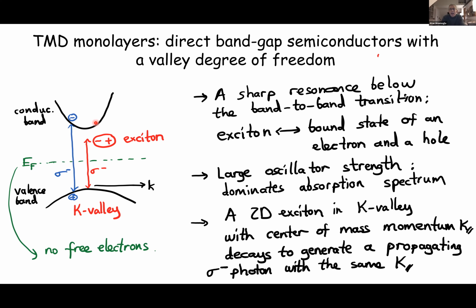But as I've been arguing, the system has strong interactions, and indeed the electron is strongly bound to the hole that it leaves behind, or it can be strongly bound, and lower its energy dramatically to form a bound state, which we refer to as an exciton. Now, the stronger the binding of the electron and hole is, the larger the oscillator strength of this object is. Because remember that when an exciton annihilates, it generates a photon, and if the electron and hole are strongly localized, then it is much more likely for them to find each other, so to speak, and recombine or be generated. And indeed, in 2D semiconductors, the absorption spectrum is dominated by excitons.